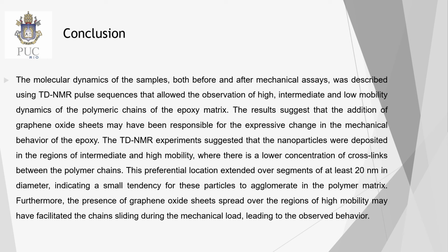So this experiment suggests that the nanoparticles were deposited in the regions of intermediate and high mobility, where there is a lower concentration of cross-links between the polymer chains. This preferential location extends over segments of at least 20 nanometers in diameter, indicating a small tendency for these particles to agglomerate in the polymer matrix. Furthermore, the presence of graphene oxide sheets spread over the regions of high mobility may have facilitated the chains sliding during the mechanical load, leading to the observed behavior.